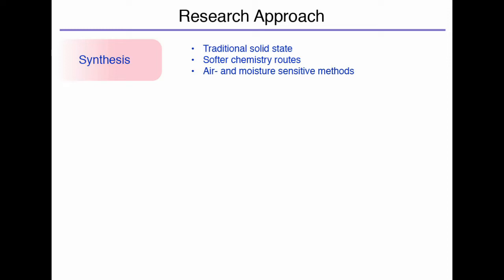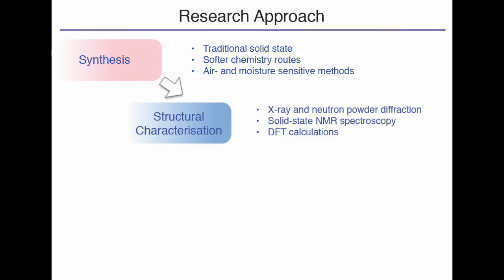Occasionally, we can use softer chemical methods, known as sol-gel methods, and increasingly, we're starting to use more air and moisture-sensitive methods based on the fact that the application is moisture and air-sensitive. Once we've made our materials, they then undergo comprehensive structural characterization using a variety of different complementary techniques. And essentially what we're trying to do here, using things like X-ray neutron powder diffraction, is look at the long-range structure of a material. And we combine this with a complementary method known as solid-state NMR, and that looks much more closely at the local structure of a material. So by combining the two, we're getting both the long and the short-range information we need.